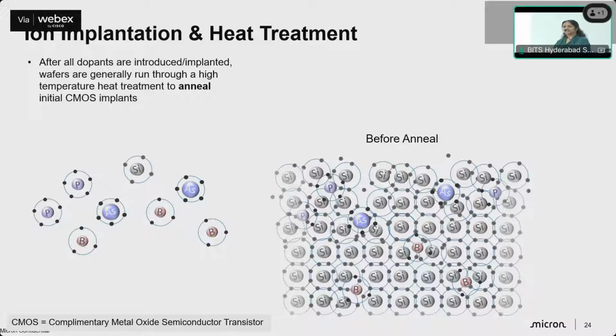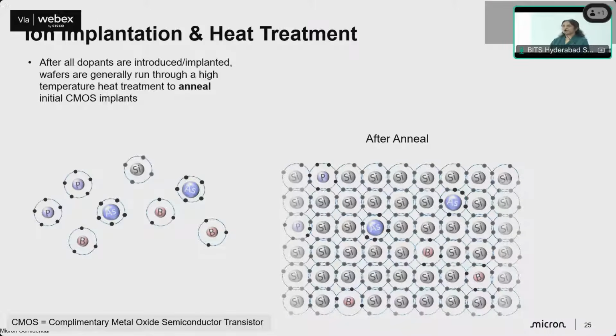Ion implantation, like I said, depends on the type of element you use. For example, boron, a small element, can go very, very deep in your silicon film, whereas phosphorus, which is a larger element, will tend to stay at the top, depending on how much it penetrates. It does disrupt the film a little bit, then you anneal it. If you count the number of electrons around, say, arsenic, the number of electrons has increased, whereas around boron, the number of electrons has dropped by 1. This is how you have created an excess of electrons or created a hole in your substrate.